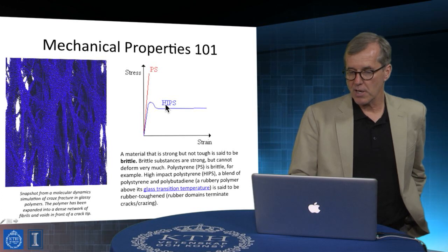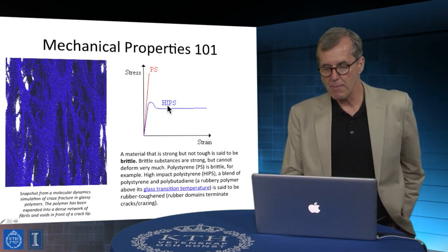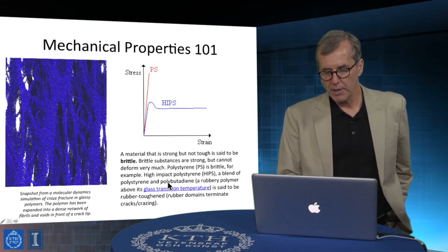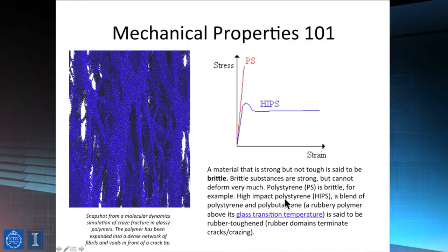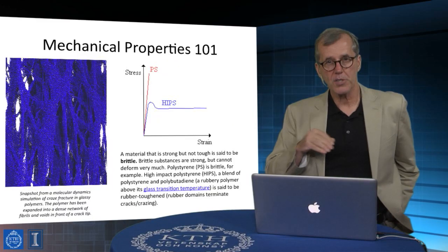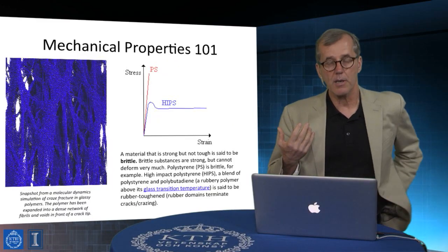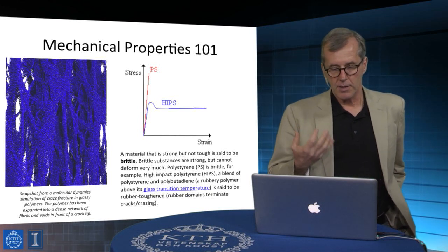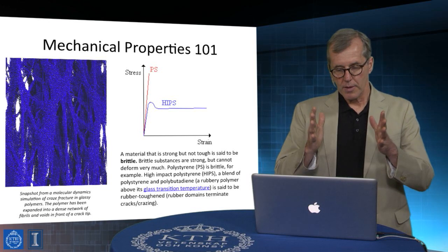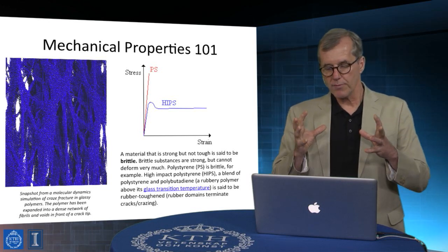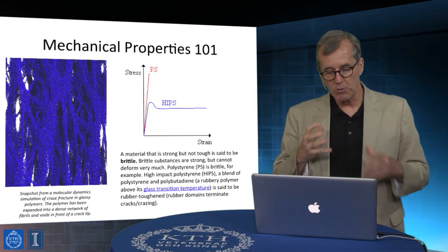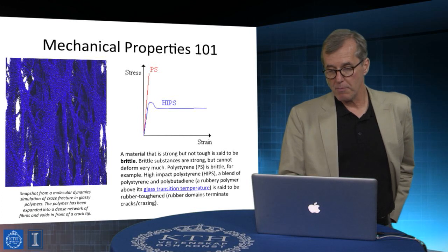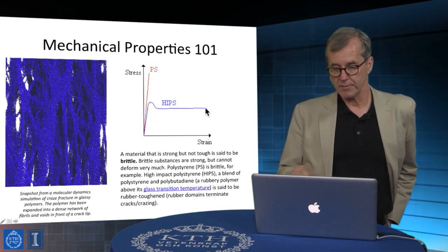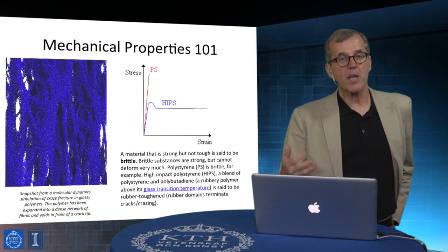A way that actually gets dealt with is to make a material that's called high impact polystyrene. And whereas polystyrene is brittle, high impact polystyrene is not, because it's a copolymer of polystyrene with a certain amount of butadiene. Butadiene and polystyrene are not compatible, so the butadiene is segregated in a rubbery phase. And these open areas, when they start to form, actually get blunted in the rubbery phase. So it frustrates the formation of crazes, and it makes the materials extremely tough. Right? So that's why these compounding ideas are really important.